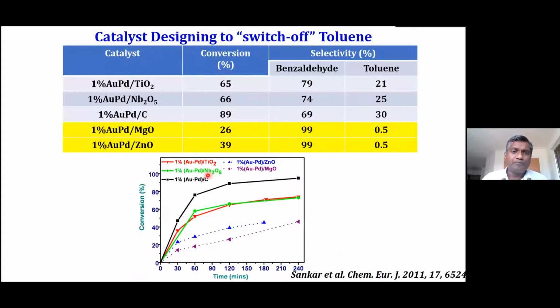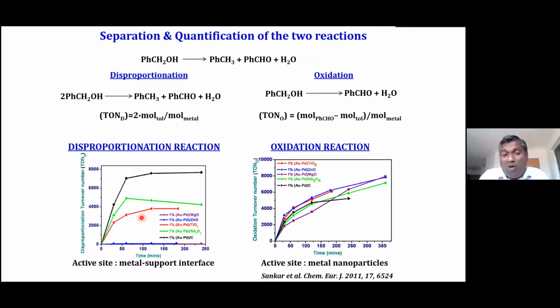Now, if we look back, the most active catalyst is not the most active because it is very active for the oxidation reaction. It is because of an additional unwanted reaction happening at the metal support interface. So how do we come to know that? If we change the support, we can see a change in the activity for the disproportionation reaction. That shows that the metal support interface is the active site for this particular disproportionation reaction. Whereas even by changing the support, we don't see much change in the activity for the oxidation reaction.